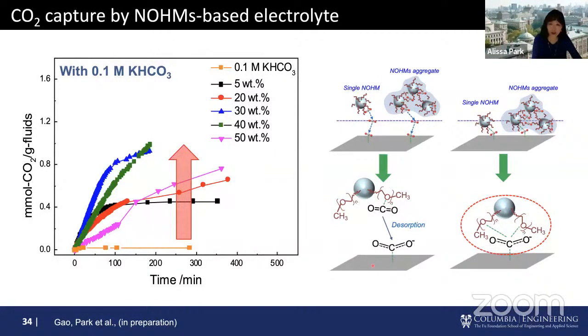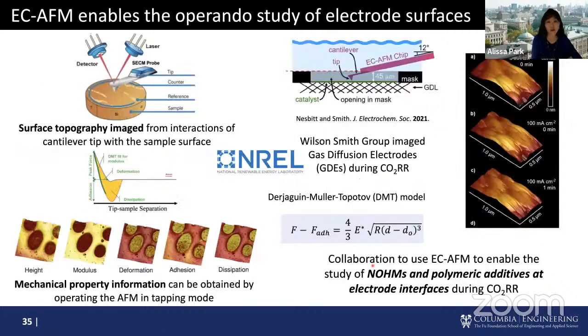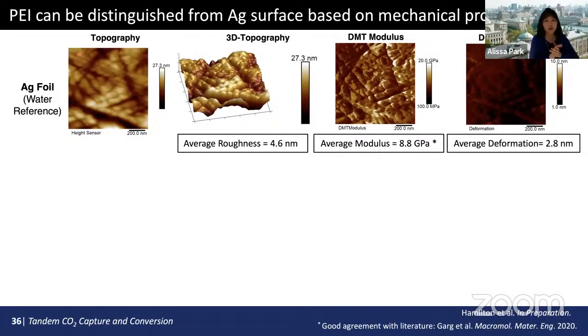So in order to really understand where NOHMs is and how they interact with the electrolyte electrode interface, we went to NREL. My colleague, Wilson Smith, has a very interesting system of EC-AFM, really understanding the surface at the interface and what's happening in the electrolyte system under applying different potential. We started with silver foil, which is a very simple system. And this is the silver foil just with water on top.